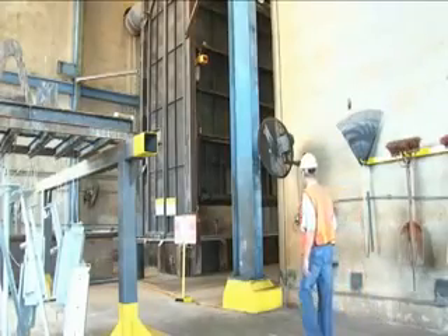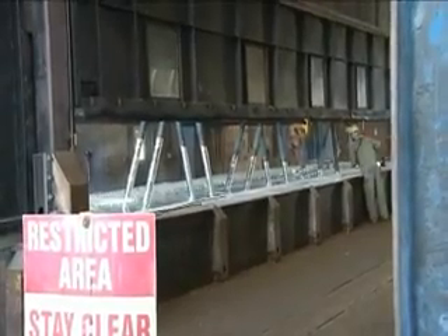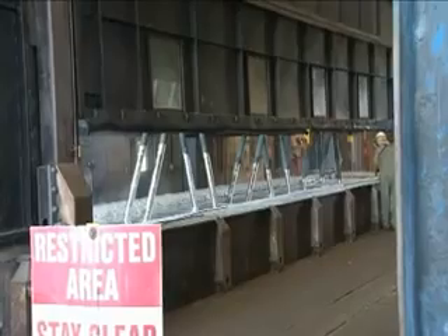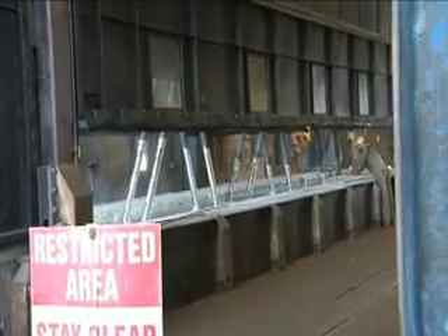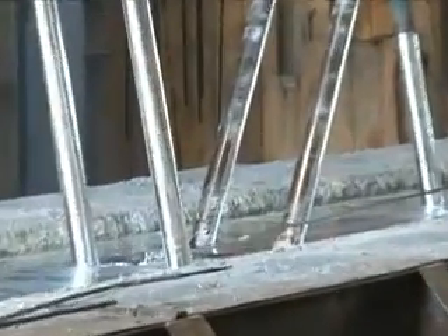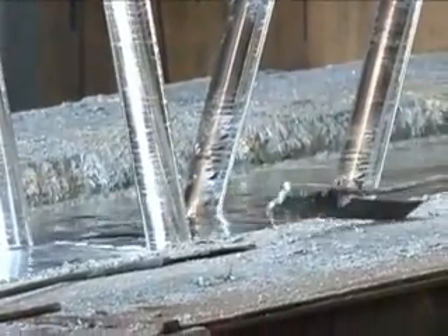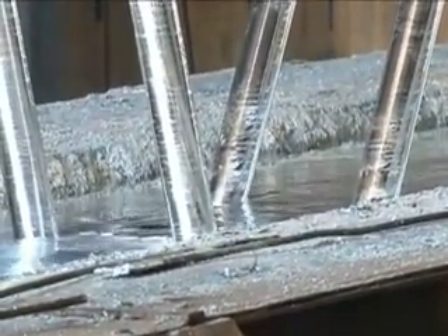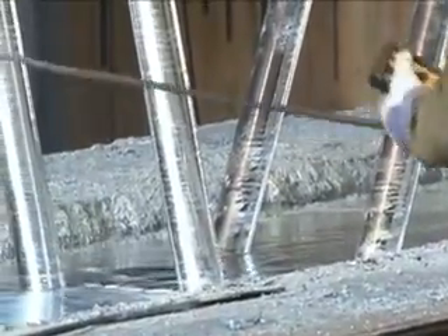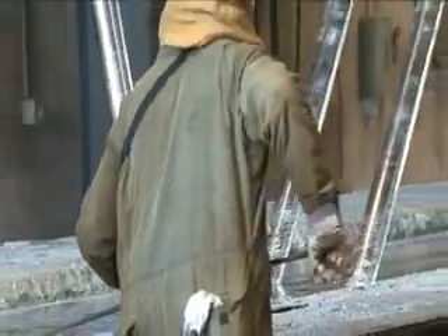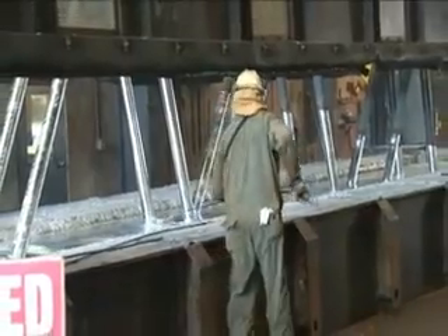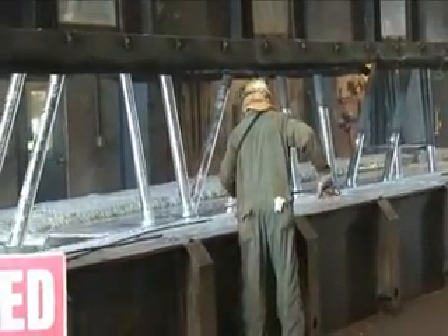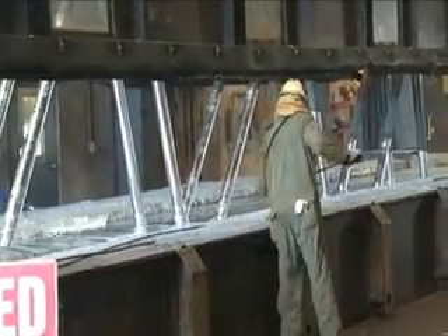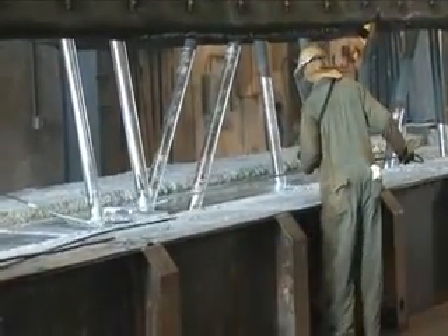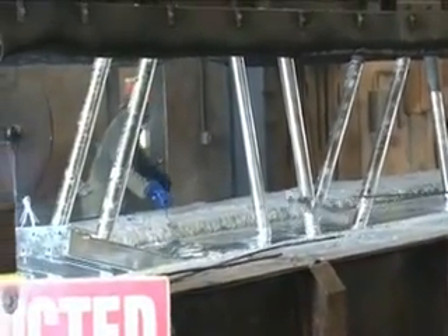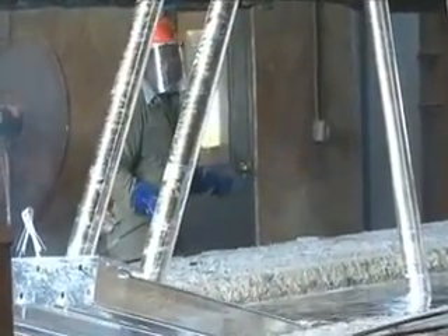After the galvanizing, the tank doors are opened and the trusses are swept and slowly raised. What they're doing now is what we call sweeping the kettle, because when the steel's in there and the product's in there, it puts off these iron oxides, which makes the skimmings on top of the kettle. So to keep that from getting onto or sticking to the product when the product's extracted out of the kettle, we sweep it, we skim it back. And then as the product is slowly extracted, they keep skimming, because all the time it's in there, it's creating the iron oxides.